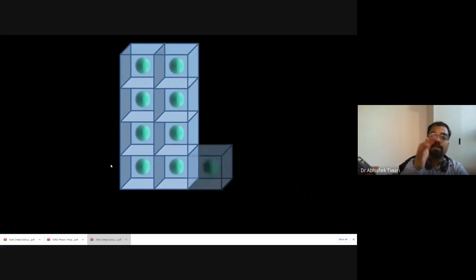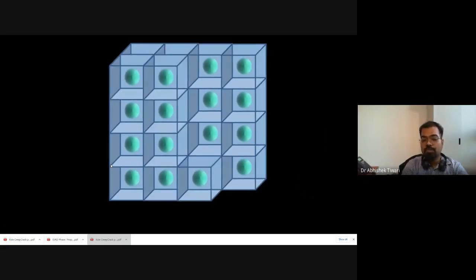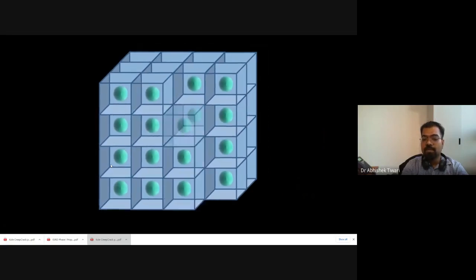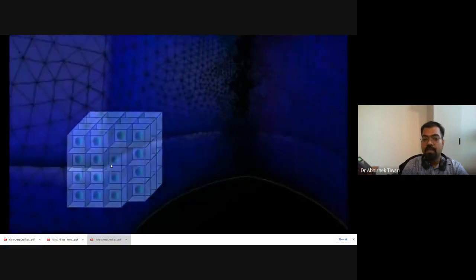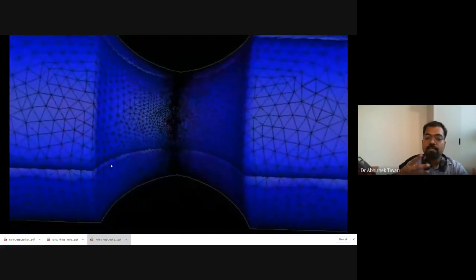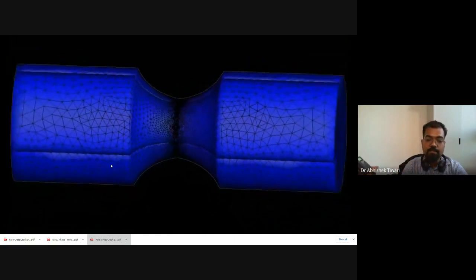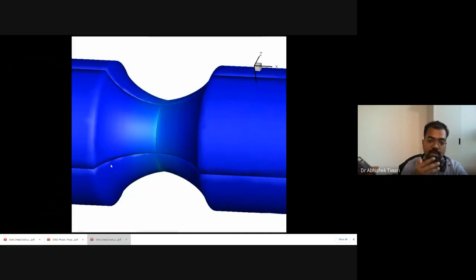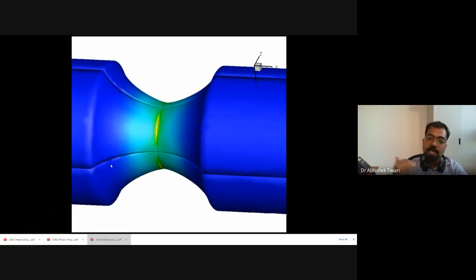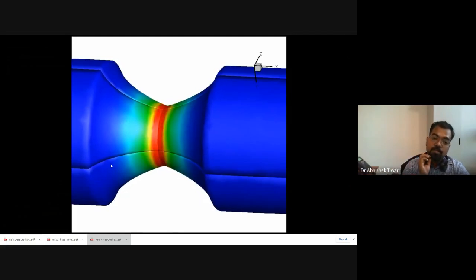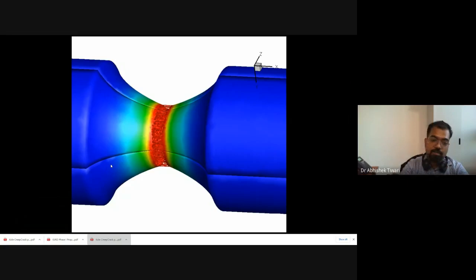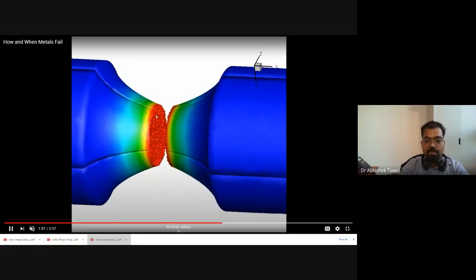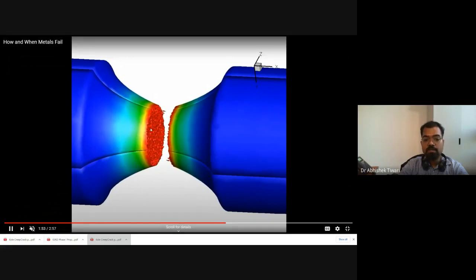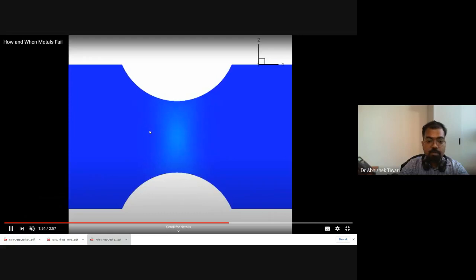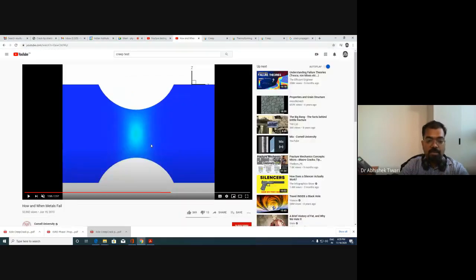Using this idea, you accumulate this, so you create more and more cubes which have more and more voids. So then you are somehow generating the real microstructure of the material, and then you can use the mathematics you have got from one small unit cell kind of thing, it's not the real unit cell, and you can simulate that tensile test specimen by applying that same mathematics of that small cuboid in the simulation. You periodically arrange those cuboids and see in the simulation also a similar structure to what you will get experimentally.